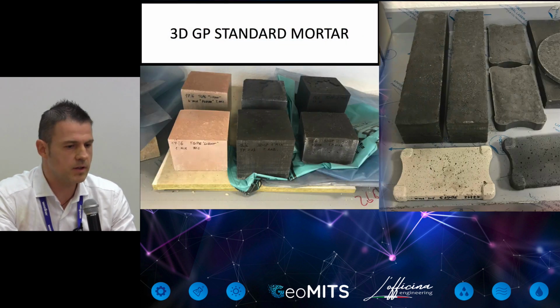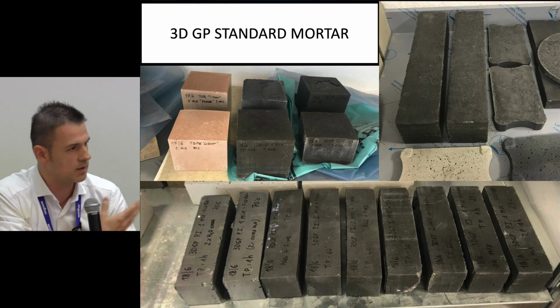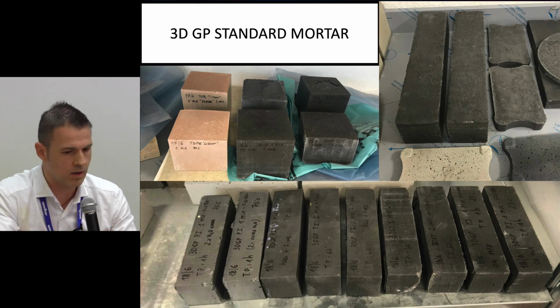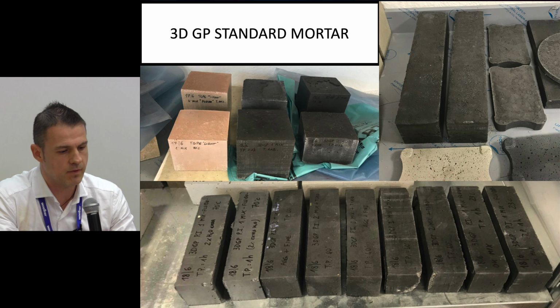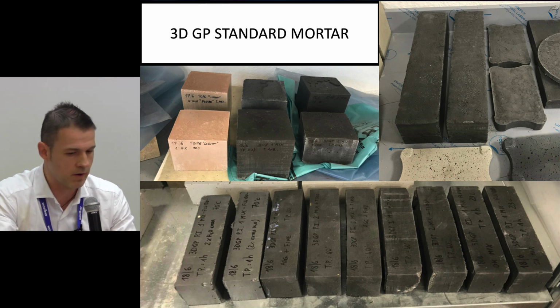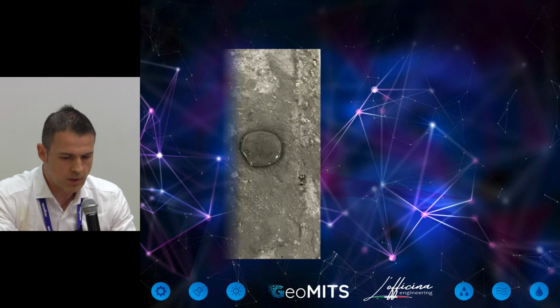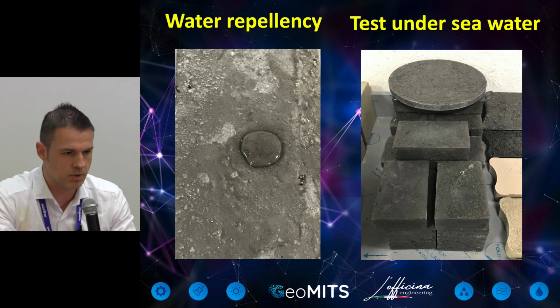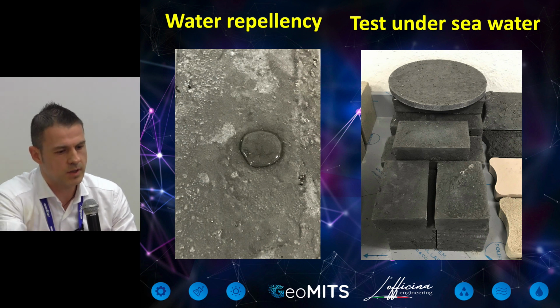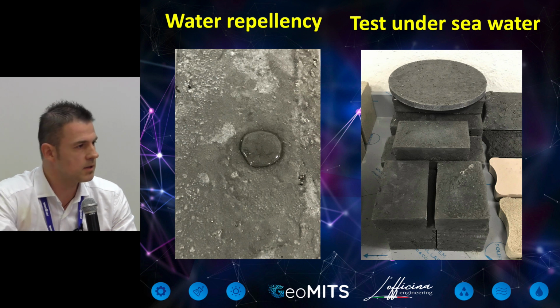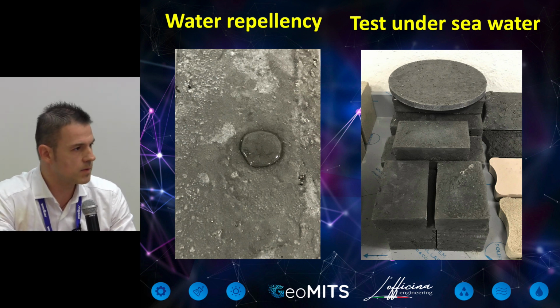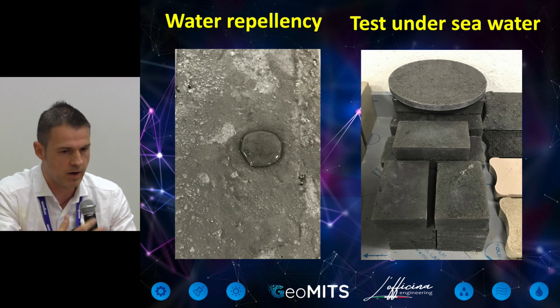So we start with the 3D standard mortar. That is the same mortar that with Andrei and Marina we printed a lot of times. And so I tested several mixes, sometimes changing the workability to prolong a little bit the setting time. So this was a test of 2 weeks ago, so very recent. And I prepared a lot of different samples, because with 50 kilograms I have a lot of material. And after a few days, you can see that the product becomes water repellent without any additives, just because of the chemistry and the reaction of geopolymer.